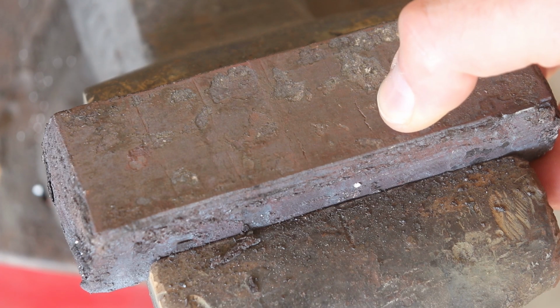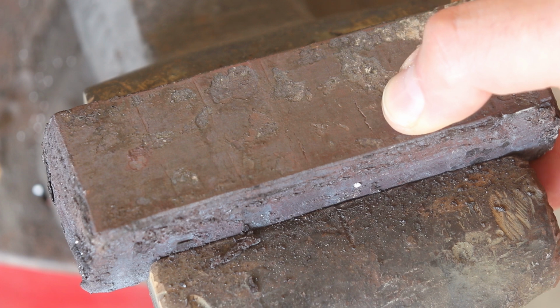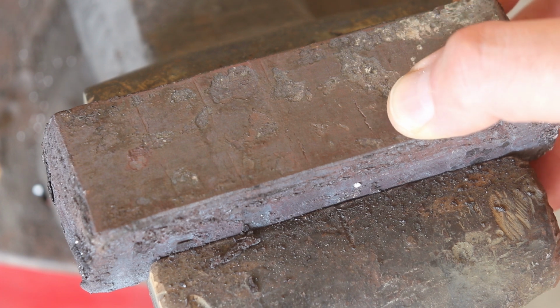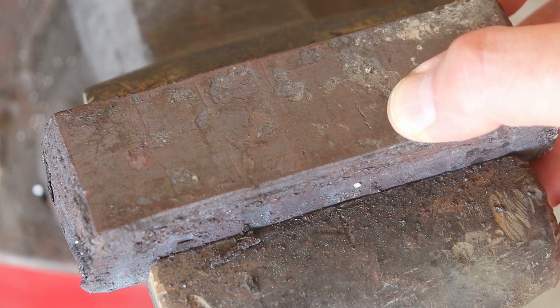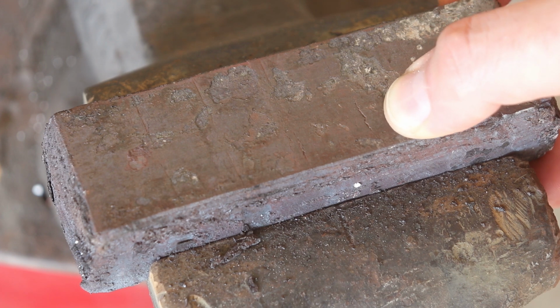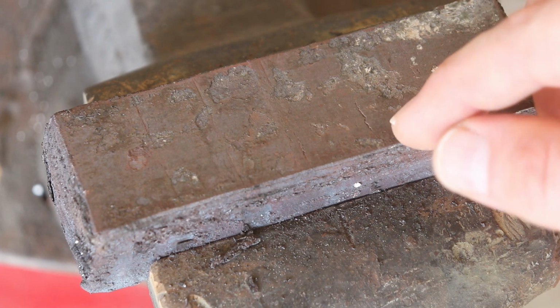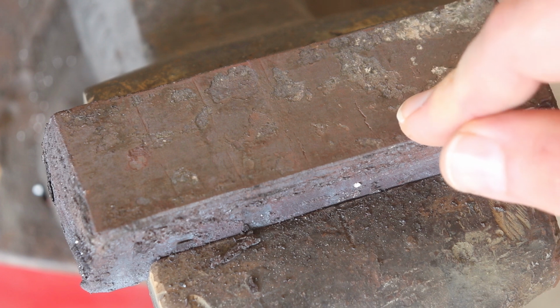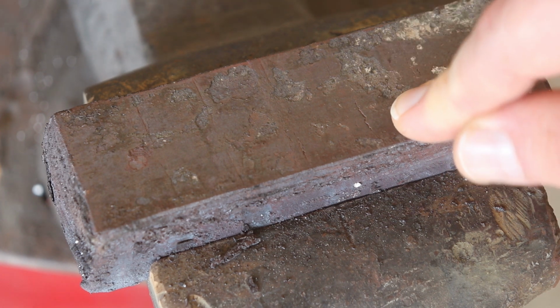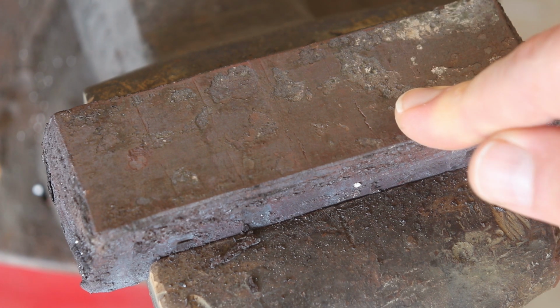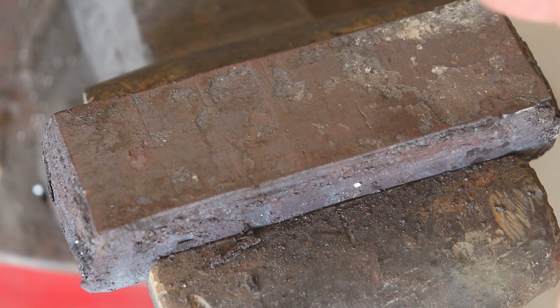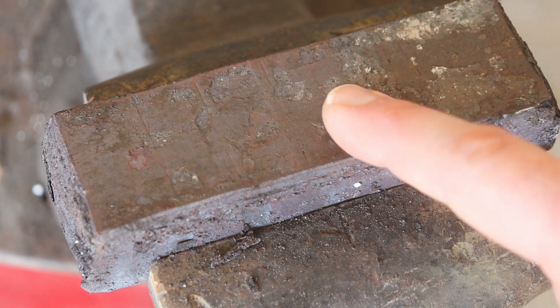You can see right here, there's this little crack in the surface. Now this is probably just a crack in the scale on top of the steel, but I don't know that for sure. So I'm going to grind it down with an angle grinder, make sure that there are no delaminations before I forge it out into a long bar to cut and stack. Because if this is a crack in the steel and I forge this down thin, I'm just going to be forging that crack deeper and deeper down into the billet, and that's obviously no good. Now this isn't a step that everybody takes, and it does take a lot of time, but if you don't do it, you could potentially risk ruining the entire piece of Damascus. So to me, it's worth every second.